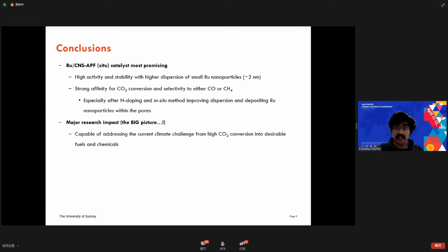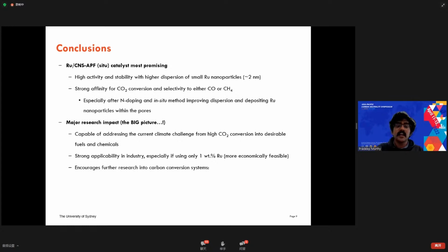So the major research impact, this catalyst has shown very strong capabilities of addressing the current climate challenge, from reaching high CO2 conversion levels into desirable fuels and chemicals. It would have a strong applicability in industry, especially if using only 1 weight percent ruthenium, as ruthenium is expensive. So if you use less, it could be more economically feasible if sufficiently active.